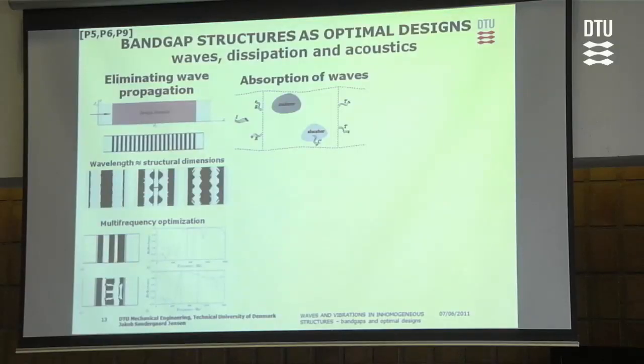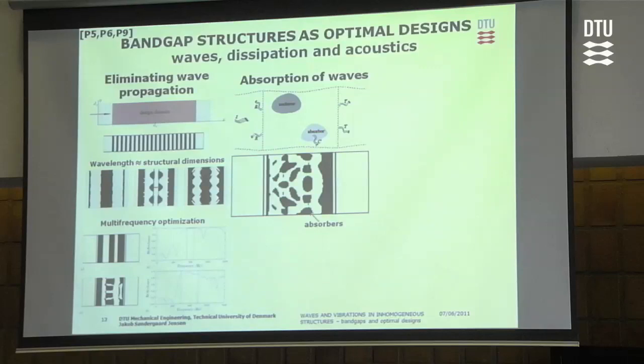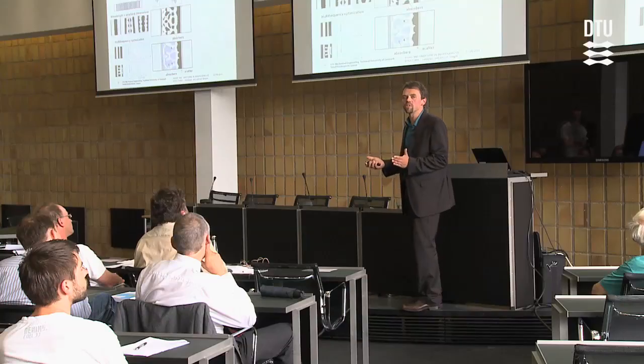We also modified the optimization problem to focus on dissipating rather than reflecting waves — studying how to distribute absorbers and stiff scatterers to maximize dissipation. The approach allows waves to pass the first boundary, reflect at the rear boundary, and a distribution of absorbers dissipates the waves. Including both absorbing materials and stiff scattering materials in the design domain improved performance slightly.